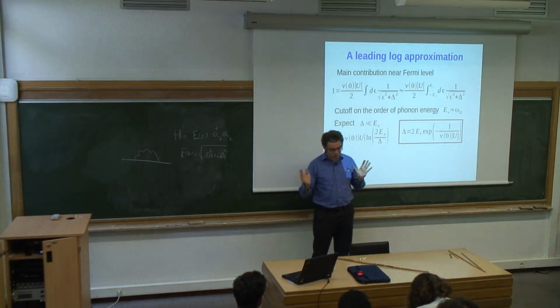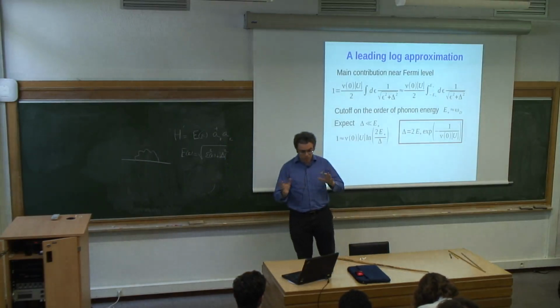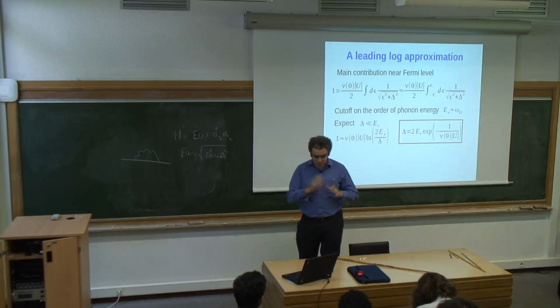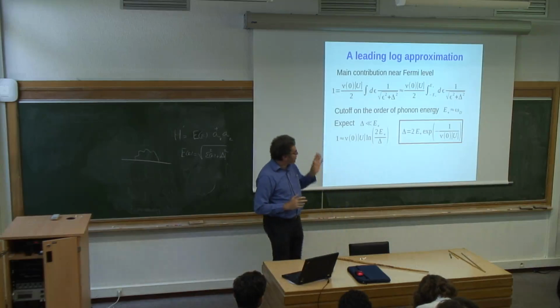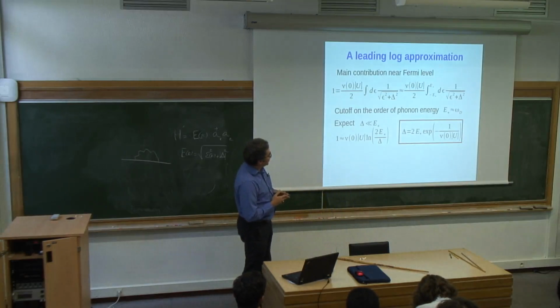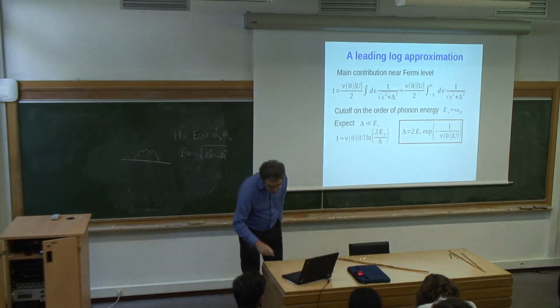And then if you want to obtain the critical temperature, if you don't worry about coefficients, you can just say that by order of magnitude, the critical temperature should be of the order of that energy gap within some factor of order 1, and then it turns out that this factor of order 1 can be calculated from the same type of approach, and it turns out to be approximately 3.5.